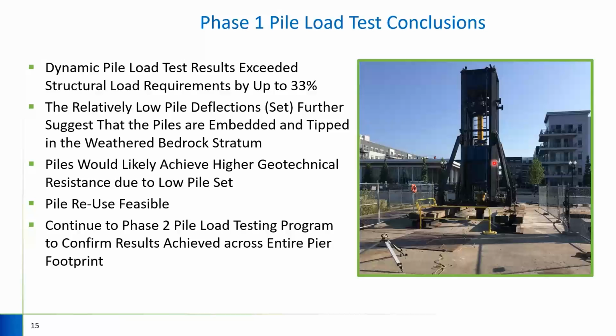So some of the overall conclusions from phase 1 were that with the dynamic pile load testing, we were actually able to exceed the full structural design loads by up to 33%. For the relatively low pile deflections and sets, it was determined that we can likely get additional geotechnical capacity out of this location, or out of these piles themselves, and that the pile reuse was feasible and we could move on to the phase 2 pile load testing program.